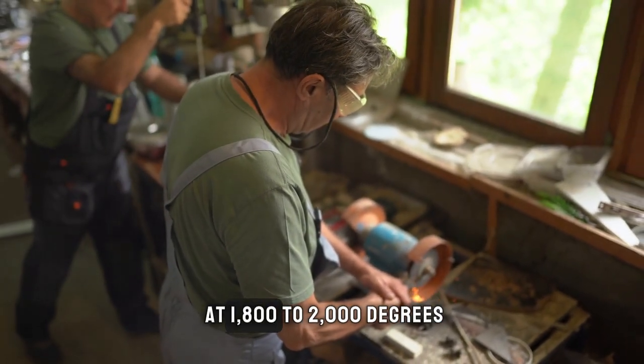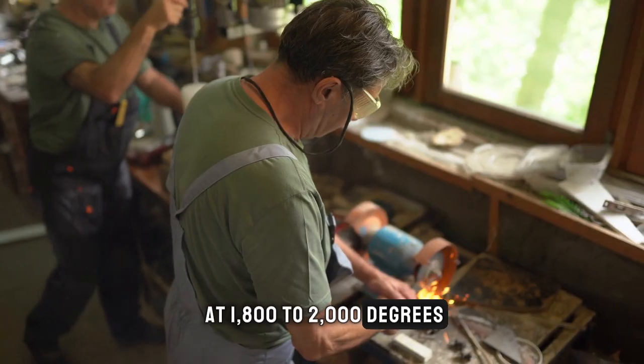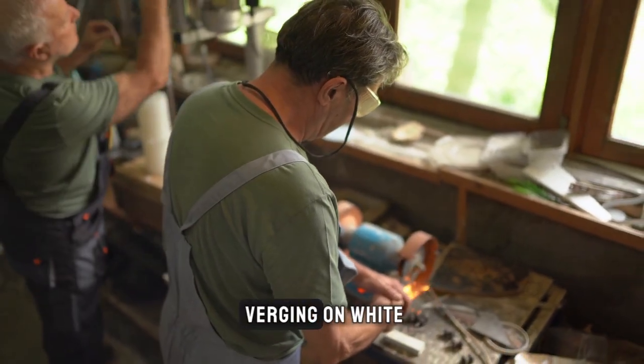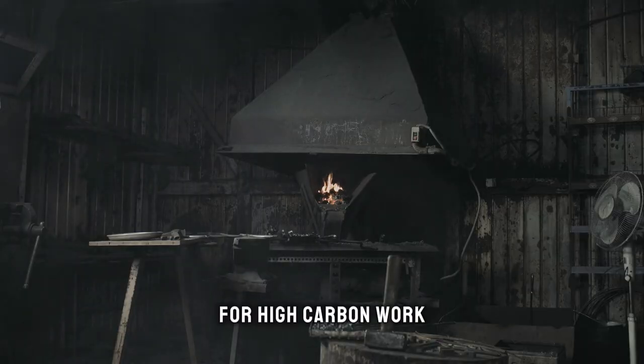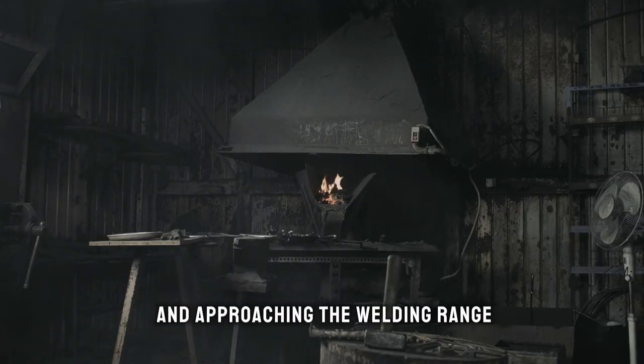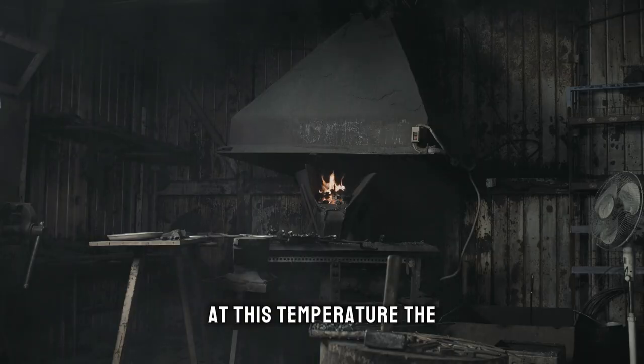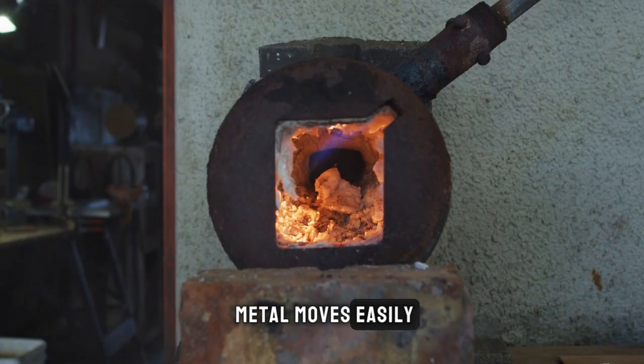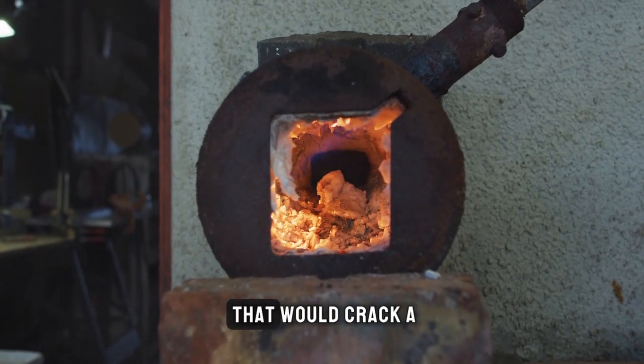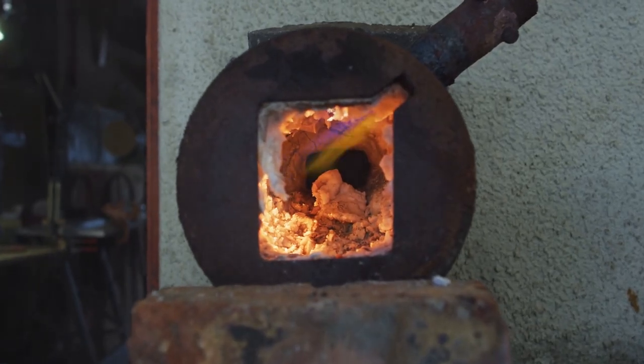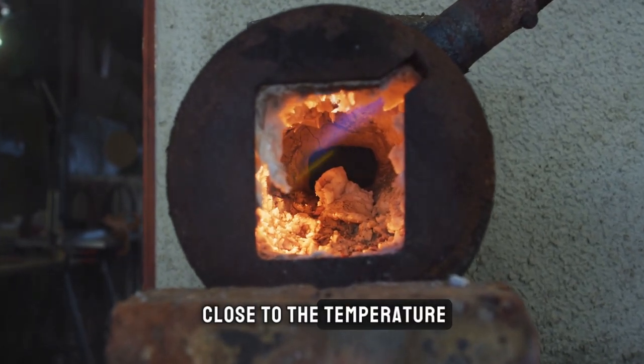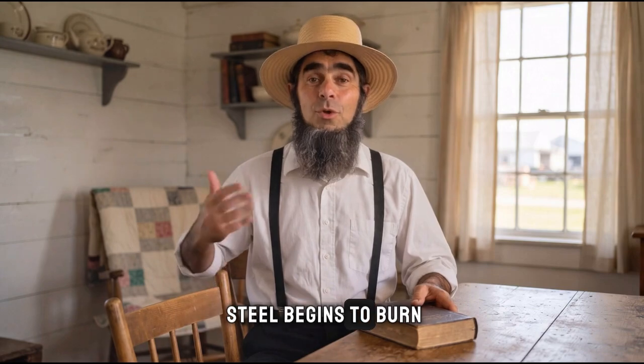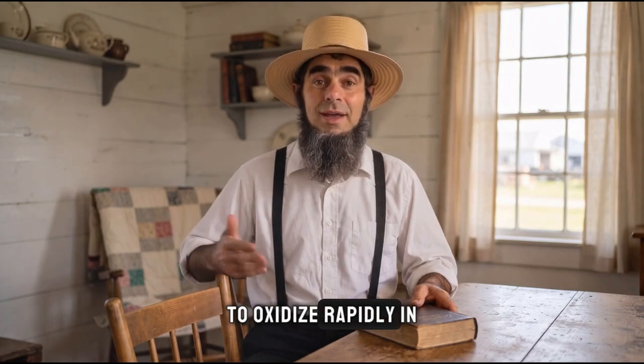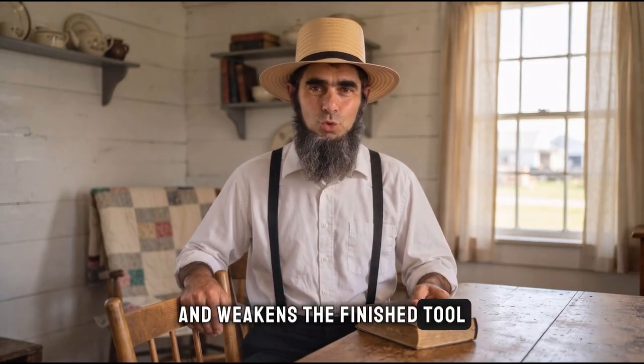At 1,800 to 2,000 degrees, a bright yellow-orange verging on white, the steel is at maximum forging temperature for high-carbon work and approaching the welding range. At this temperature, the metal moves easily and forgives hammer blows that would crack a cooler piece. But it is also close to the temperature at which high-carbon steel begins to burn, to oxidize rapidly in a way that damages the carbon content and weakens the finished tool.